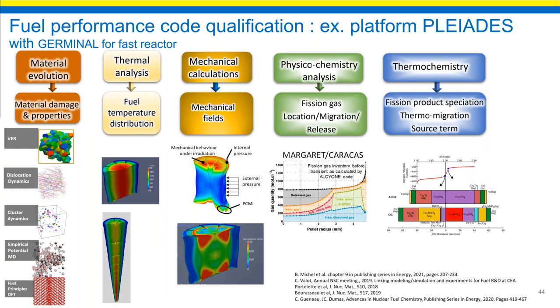And the combinations of all these components can predict all the effects we have seen. I have to say for the material evolutions on the left part that several scales are used for the prediction of damage and properties evolutions, from the atomistic modeling up to very representative elementary volume that take into account not only the compositions but also the microstructure like grain size and grain boundaries and porosities and the shape of porosity.